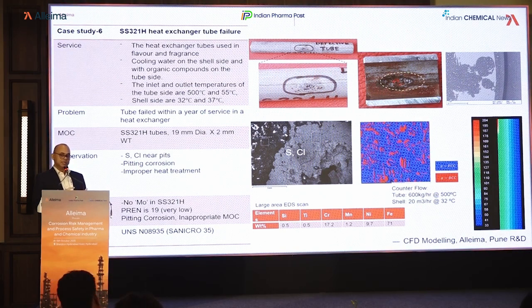And then there was pitting, and when we looked into the metallurgy of this, there was another phase. So this was basically austenite phase, and then we could see another phase, the ferrite phase. So your heat treatment, of course, was not good. But now the question is, if it would have been the right quality, would it have worked? Probably not, because you have chloride also in this process, and at the same time, if you look at the temperature, that is on a much higher side.